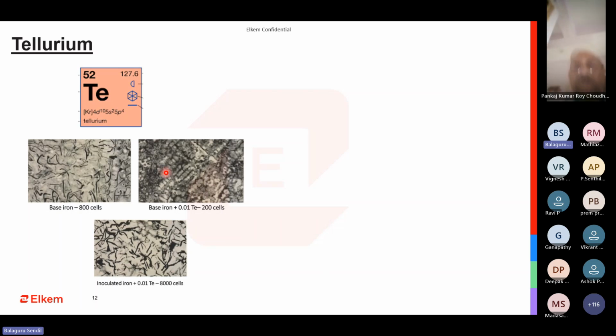Okay, I take this condition and then I try to use my best inoculant. I use a strontium based one, which is supposed to be the best inoculant in the market. I do that, and I do end up solving the problem. I do get back a bit of type A, but it is not as good as the base iron. Though the cells have increased, the microstructure is not very favorable.